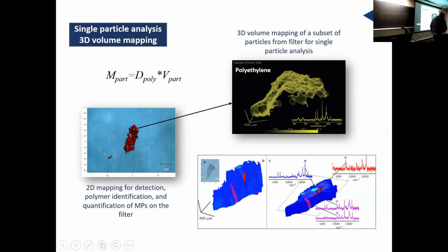And then we have this pigment that we have found in every sample that we analyze. Every sample, sediment, water, no matter where the water is from, we found this pigment. So we know that, for example, this particle came from the recycling process, because when the industry is making new plastics, they don't mix polypropylene with polyethylene. Those polymers don't mix very well, and they produce low quality plastics. So we assume that this particle came from a recycled process or a recycled product.